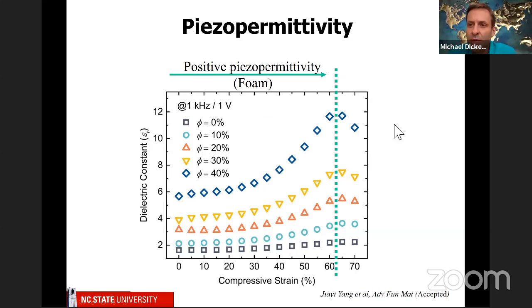Where this gets really surprising and interesting is to the right of this, you'll see that once we get rid of all the air, we actually start seeing a negative piezo permittivity. In other words, the dielectric constant decreases. And we believe that this is due, and I'm teasing you here a little bit, and I'm not showing you all the details, but I'd be happy to talk more about it. We believe that the liquid droplets are actually getting squished and changing the shape of the filler within this composite.